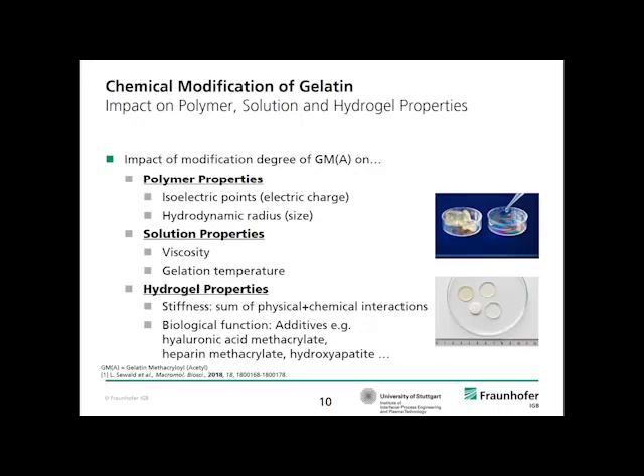By doing so, we can control the properties of the polymers on the one hand side, like the isoelectric point of gelatin, the electric charge of the molecule, or the hydrodynamic radius, which is something like the size of the molecules. And this again will affect the intermolecular interactions and then also the solution properties. So the hydrodynamic radius, for example, will affect the viscosity of solutions or the gelation temperature. And last but not least, we also, of course, can then adjust the hydrogel properties by the amount of cross-linkable functions that we use in terms of the stiffness of the gel, the swellability of the gel, or by changing the composition, also biological functions, as I said, by addition of other biological components.